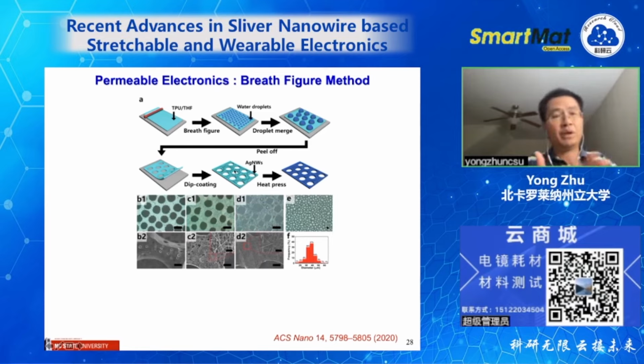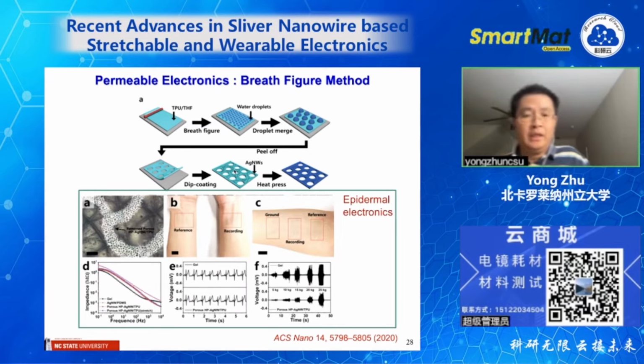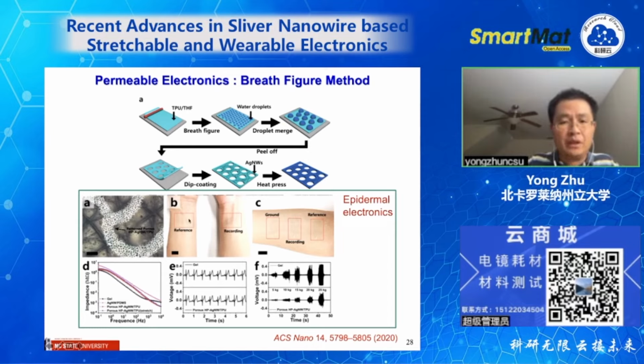And in this case, we have nanowires on both sides, right. And then we can have it directly on the skin. We can do something called epidermal electronics, right? So we put the reference electrode and recording electrode directly on the skin. And you see what happens with this porous electrode: it's not only highly conductive and permeable, but also nearly transparent. Very high transparency. You can barely see this.